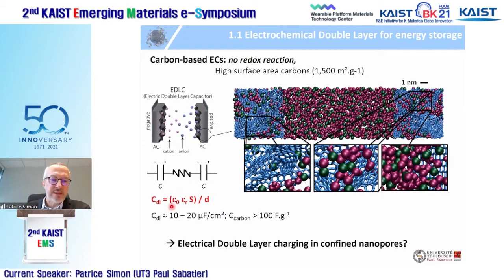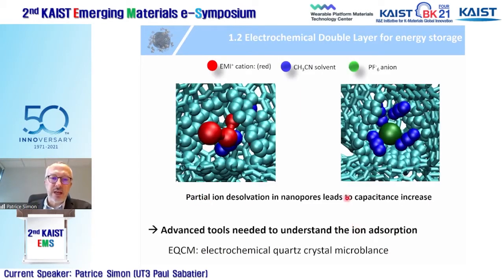This double layer capacitance is proportional to the dielectric constant of the electrolyte and varies with the inverse of the approaching distance of the ion to the carbon surface. When you have a super high surface area, we can reach high gravimetric capacitance for carbon, when you use carbon with 1500 square meters per gram. So the challenge here is to really get a better understanding of the electrical double layer charging in confined pores.